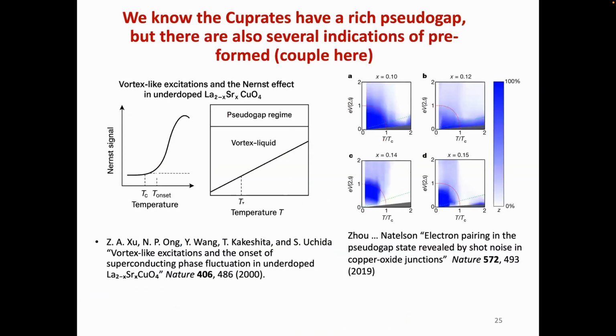I just want to show a couple other things here. And that is Ong's group a long time ago did the Nernst effect. And they were able to show that there was a vortex lattice just above TC. And so he was arguing, and it looked pretty reasonable, that above TC there were preformed pairs. And then I want to point out that Doug Natelson and group also did this, looking at shot noise in copper oxide junctions.